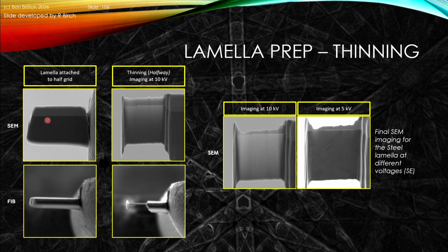So the thinning enables us to get it to electron transparency, but also enables us to remove the damage that was presented from when we did the FIB work, because a lot of the FIB work will have been done at very high probe currents and voltages to enable us to cut up material quickly. So we can now see that we have a very thin section of this sample. This is the electron transparent region that we're going to be interested in. And then we can image, and this is I think about a 5 micron by 5 micron region with a tungsten cap that's presented on this particular sample.